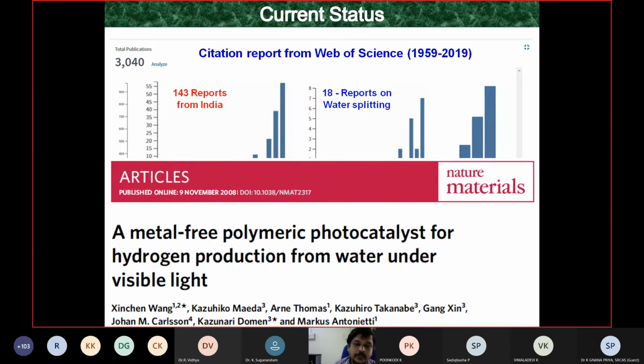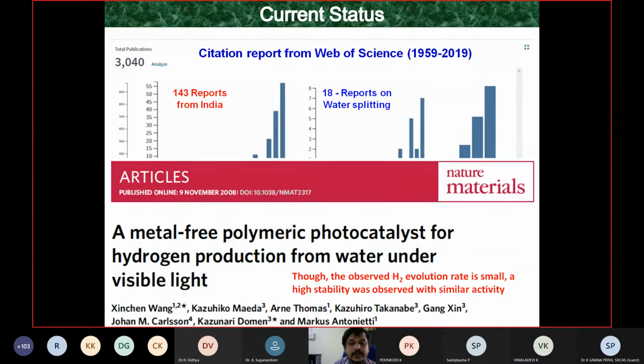Why our interest in water splitting with graphitic carbon nitride? Just look at this report, reported in 2008. They used this metal free polymeric photocatalyst, graphitic carbon nitride, as a photocatalyst for hydrogen production. They found that the hydrogen production capability is very low, but it has excellent stability. As already mentioned, if you want to go for commercialization, then you have to use a stable catalyst. So for that, we have considered this particular catalyst, graphitic carbon nitride.